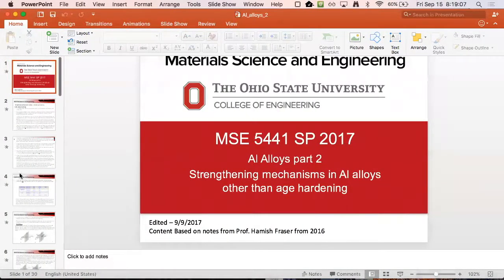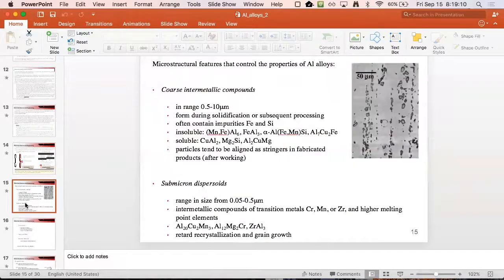A big one, so I can bring this back to aluminum. Believe it or not, I can. From mechanical behavior, do you expect materials with high stacking fault energy or low stacking fault energy to twin more readily? Mechanical twinning, deformation twinning. Low stacking fault energy twins more readily. Is aluminum a high or low stacking fault material? High. We never see deformation twins.